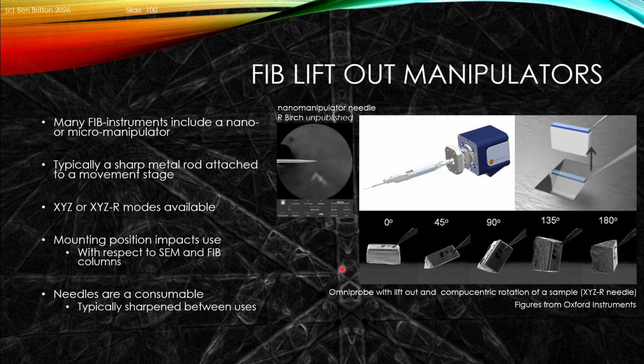So many FIB instruments include a nano or micromanipulator needle. Typically this is a sharp metal rod. It's often actually the end of this rod is a consumable that you might change, and you might also sharpen to improve the sharpness to enable you to be even more site-specific. It's attached to a very fine precision movement stage, typically nanometer or 50 nanometer encoded. And some examples will be XYZ allowable, and some will have rotation about the axis of the needle, so an XYZR, which enables you to rotate the sample like this.